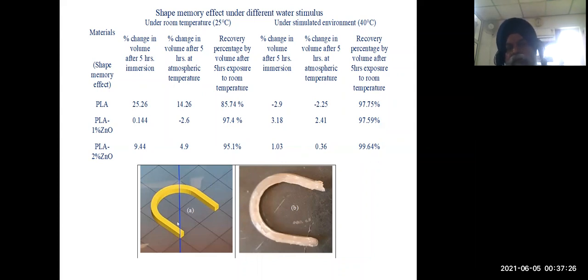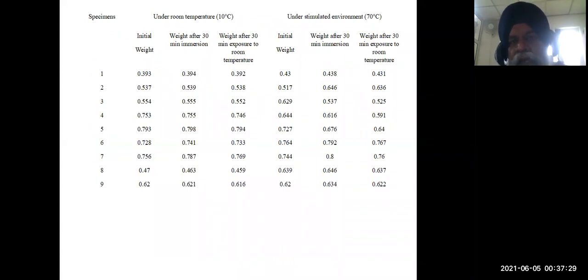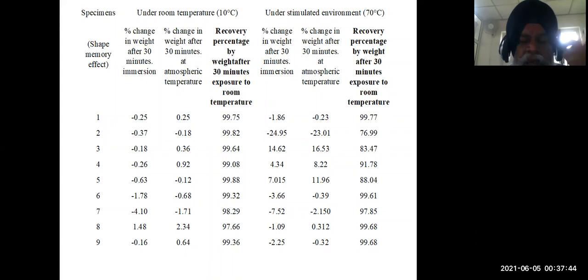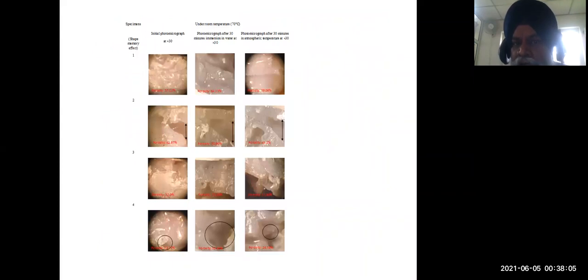Then we were a little interested to see why this is happening. So we try to see this effect based upon the glass transition temperature of the material. So we try to see the effect on the weight as well as on the volume and the dimensional feature at some low temperature and at high temperature above Tg. So if we are working near Tg, what we observed, we can have a recovery up to 99%, sometimes 99.9%. So in this particular example, what we observed is that these types of materials have a double effect, means they have two stimuli. One is the temperature and another is the moisture content. So hydrothermal effect was there, right? So we try to correlate this change in dimension with the porosity of the material. What we observed, where we are getting better recovery, the porosity was less, so we try to correlate with the morphological part of that particular component, right?